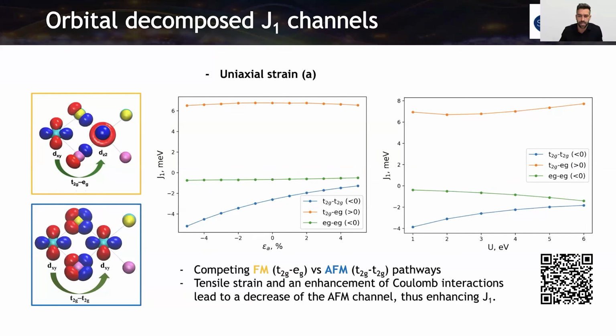Yeah. But in our calculation, we have these occupations that come from the sharing between the orbitals. And one thing is that when we increase the Hubbard U, we increase the occupation. This is something that we think has to be severely taken into account, because U is the same for the t2g and the eg, and it shouldn't be the case, because the t2g orbitals are occupied and the eg are almost empty.